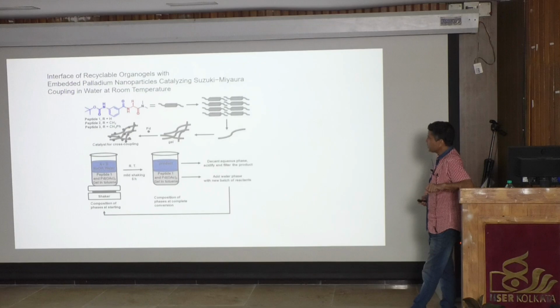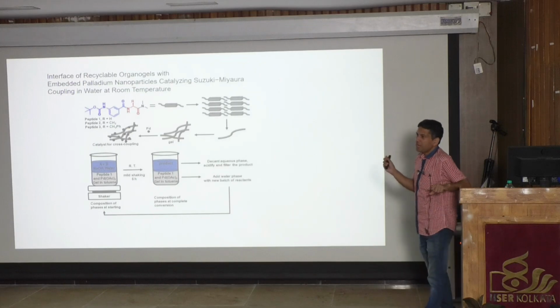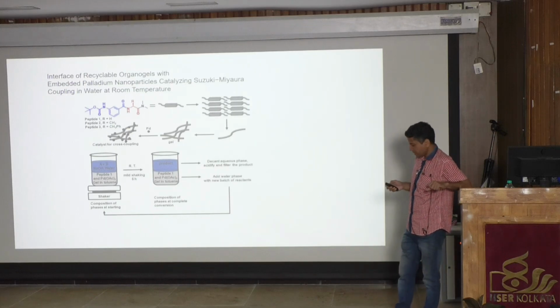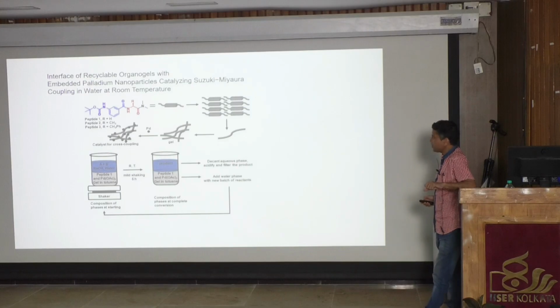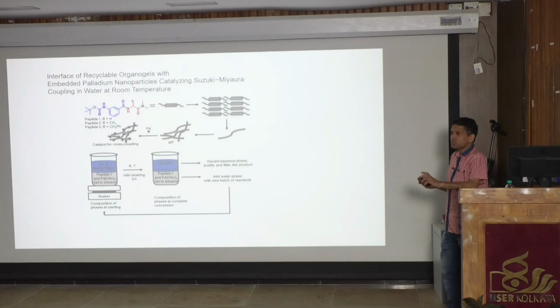And then we thought, can we use palladium nanoparticles inside the gel matrix? Then the entire gel matrix can be used for cross-coupling reactions, like the Suzuki coupling reaction. Again, the concept is very simple. We just put a layer of the gel at the bottom of a glass container, and then on top we add an aqueous solution of reagents A plus B in NaOH solution in water.